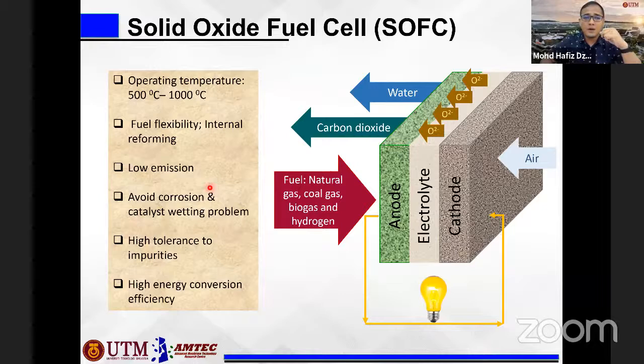And also, due to its high efficiency, it has a low emission, especially if you use hydrogen as the fuel. And because the electrolyte is solid, ceramic, you don't have any corrosion issue. You don't have any catalyst wetting problem like the other types with liquid electrolyte, for example molten carbonate and phosphoric acid, which have such issues in their operation. And also this type of fuel cell can tolerate impurities, meaning that if you have CO2 or CO or any contaminant in your fuel feed, it can still tolerate these impurities.